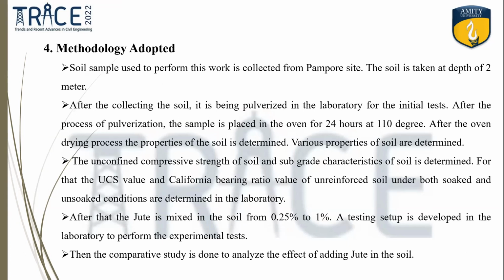Then the methodology adopted in the present study contains, firstly, the soil is taken from the Pampore site, and then it is taken into the laboratory, and it is pulverized and kept in the oven for 24 hours at 110 degrees Celsius. Then the UCS value is determined, and the subgrade characteristics of the soil are determined under both soaked and unsoaked condition. And then the jute fiber is added into the soil, with percentage varying from 0.25% to 1%. Next slide, please.